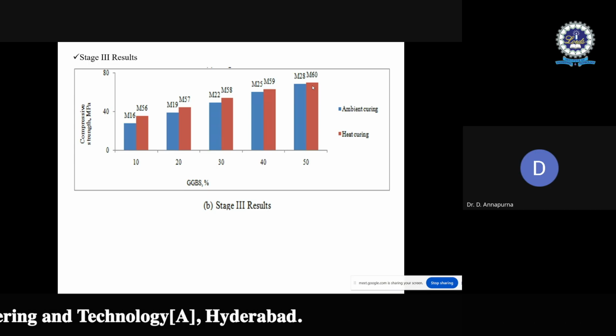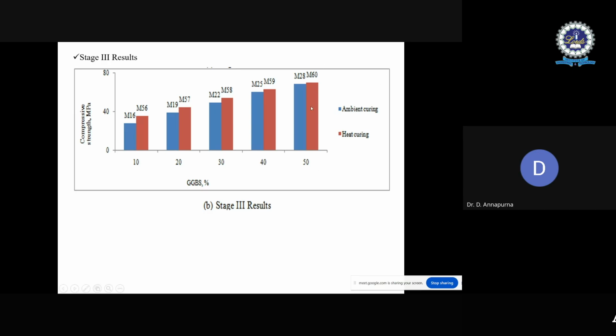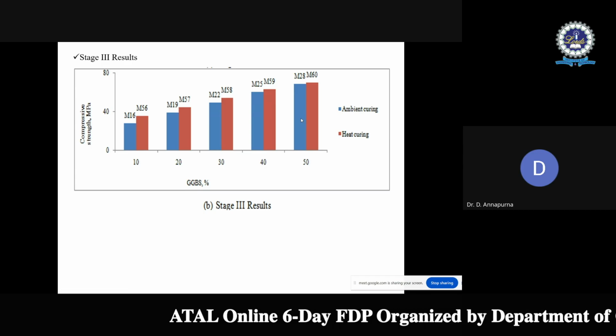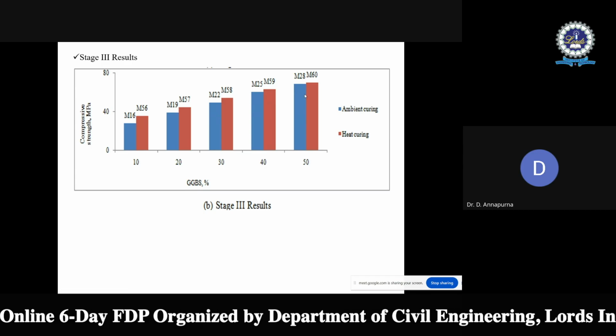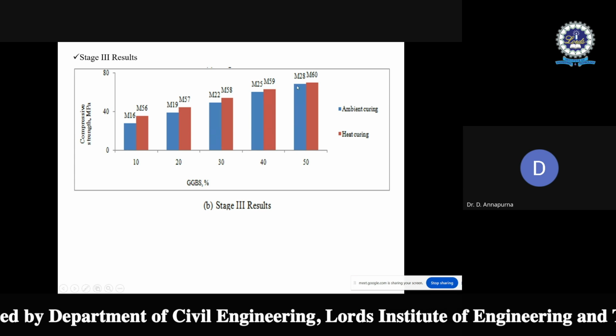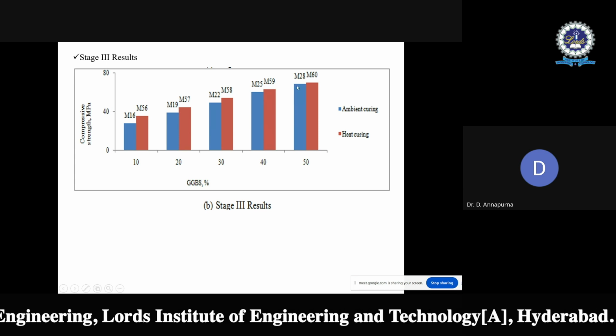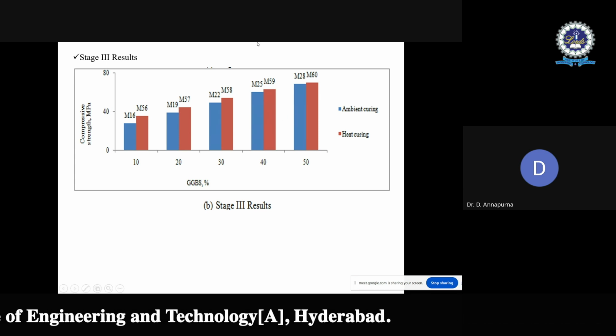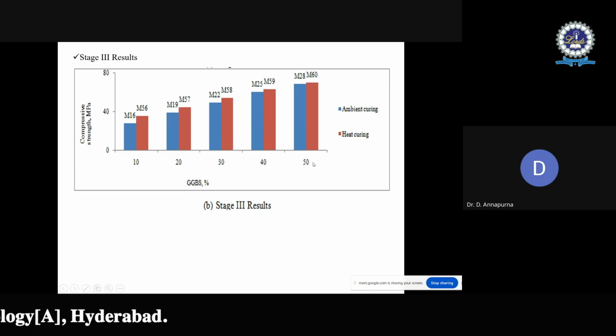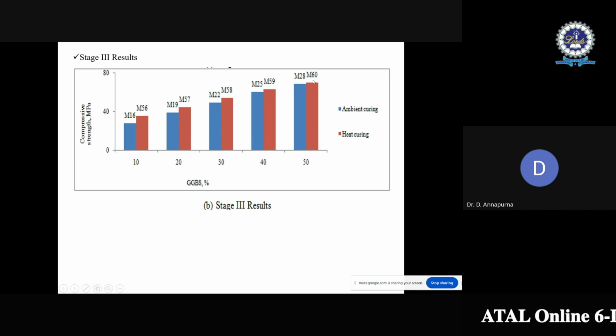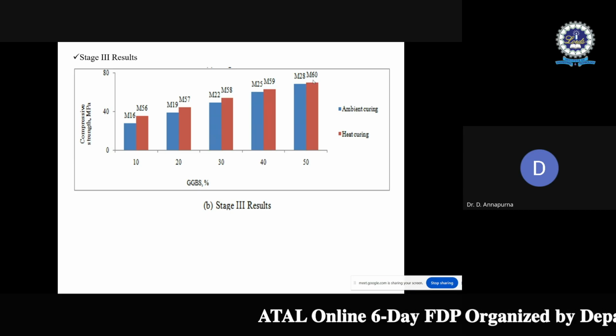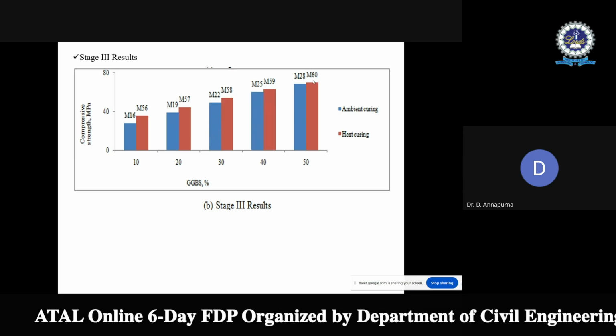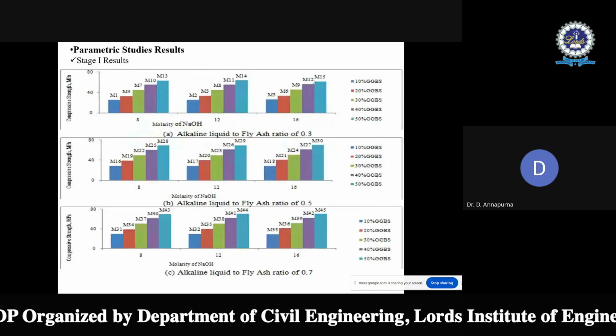The reason may be the resulting hydration due to increased calcium content. Because the GGBS addition is more, the calcium content is more, and due to that the hydration process is evolving. So in ambient curing also, because of that hydration process, it gives good improvement in the compressive strength. At higher dosages of GGBS, there is very little difference between the heat curing and ambient curing samples. And keeping practicality in view, only ambient curing is considered for the next stage of work.